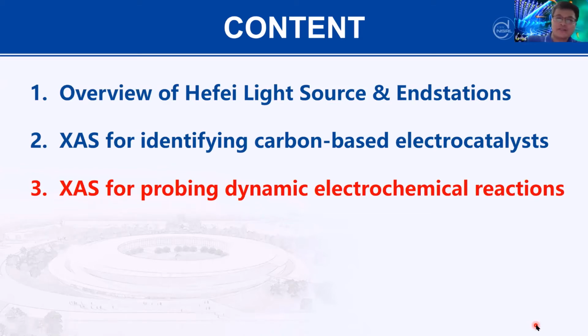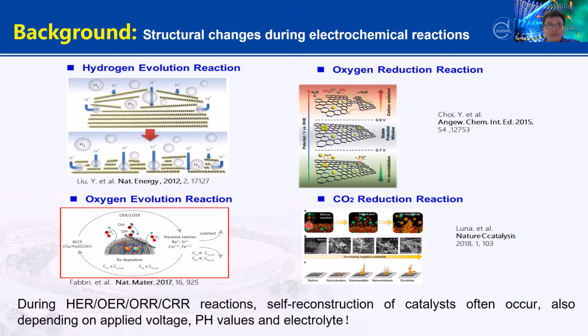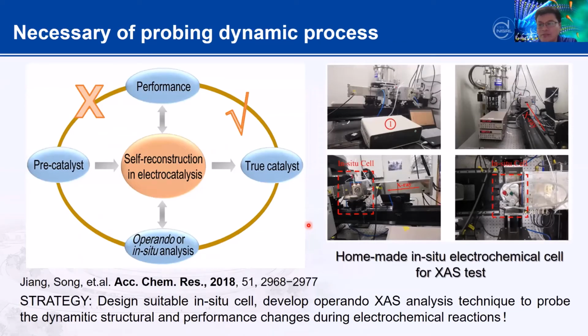In the following 50 minutes, I will try to tell some story about using XAS to probe the dynamic electrochemical reaction. As you know, in many chemical reactions, for example, hydrogen evolution reaction, oxygen reduction reaction, OER and CO2RR, during these reactions, because you use an electrolyte, you put it into the solution, and you also have the applied field. In this case, you will very often see that the material, the catalyst which you put in, is changed. This change will mainly depend on the applied voltage, pH value, and electrolyte. So how to understand this? This is what we are thinking about. You put in the electrolyte, and at this moment we call it the pre-catalyst.